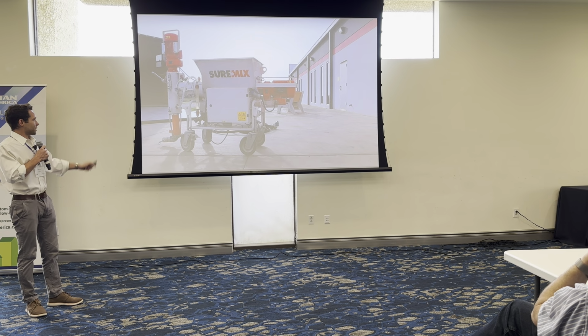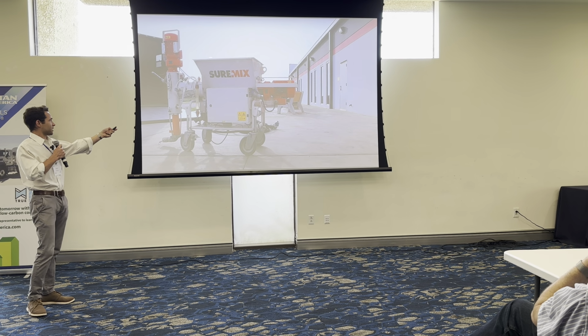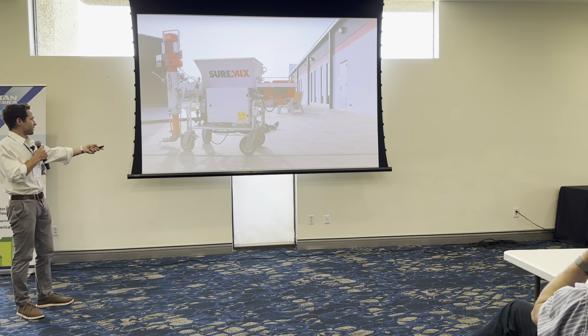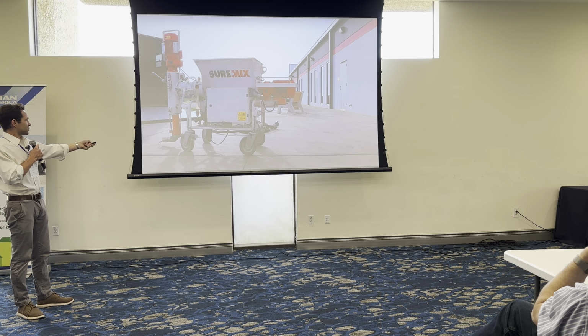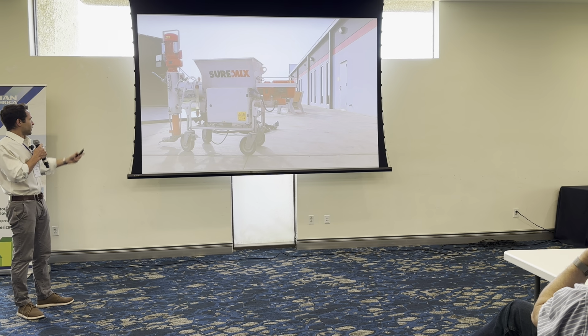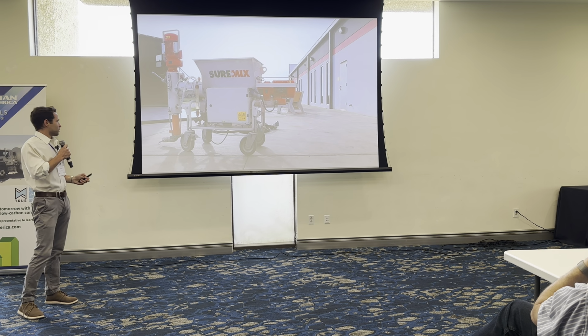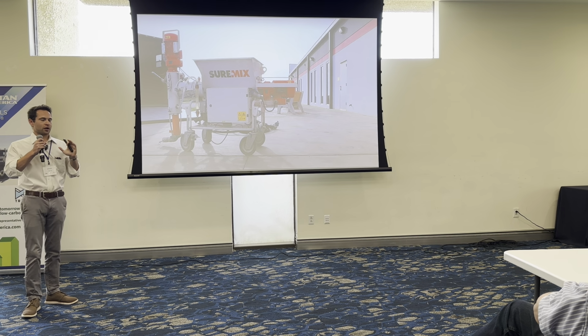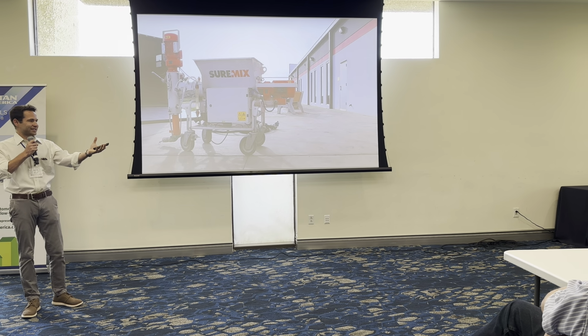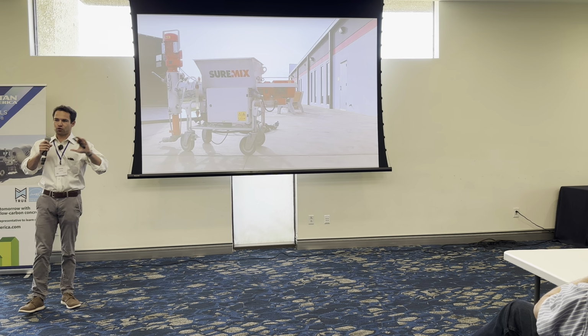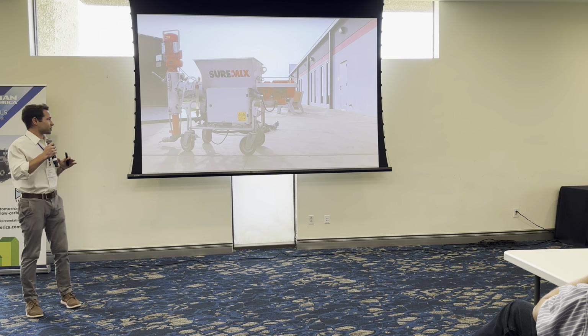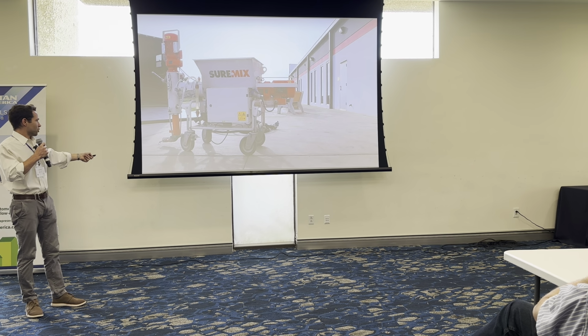This is an example of the mixer pump system. So it would be fed in through the top. You have the dry mix fed in, and then you have a hose with water that gets adjusted with this system. And then it flows through the pump into the rotor stator, which is a metal tube with a rubber gasket inside and an auger that really grinds all the material up and makes sure it's a homogeneous flow when it goes into the hose. And this is where the hose would be connected.